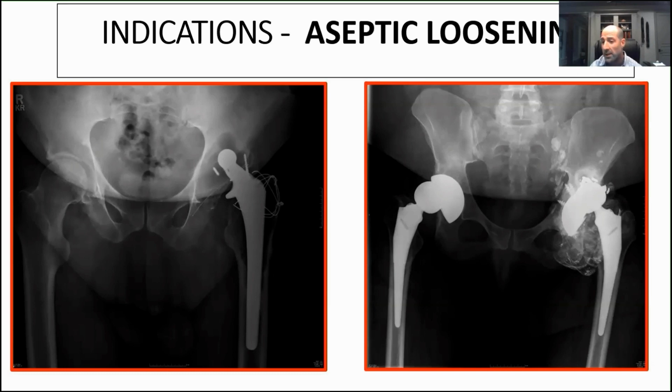That's a really unfortunate and relatively rare, I think, case where this 28-year-old female had her left total hip done 2 years ago, catastrophic polyethylene wear, and then the ceramic head simply eroded through the titanium shell. And you can see all the titanium debris. It's embedded in the bone, it's embedded in the soft tissue. It's quite toxic. This is all dead bone and fairly dramatic soft tissue compromise.